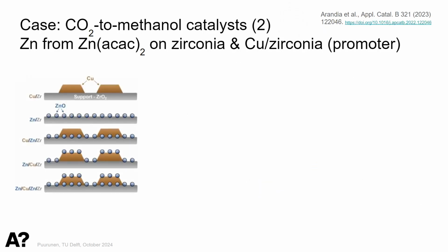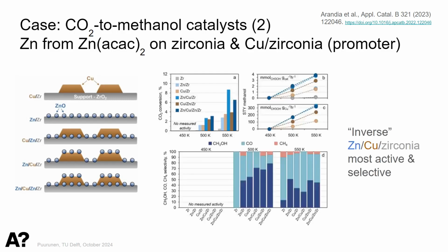Then these were tested for activity. What we did was we made a series of catalysts where, as said, copper was impregnated. We had either just copper on zirconia or just zinc on zirconia, or first zinc and then copper, or the other way around, first copper and then zinc, and we made also one where we have zinc, copper, zinc. And these were tested for activity, and we found that those catalysts where we had both copper and zinc present, and zinc on top, they were most active. So here you have the space-time yield of methanol at, well, 500 kelvin, which has been our reference temperature. We investigated 3 temperatures. Yeah, the blue ones are always the best here, and the blue ones have zinc on top.